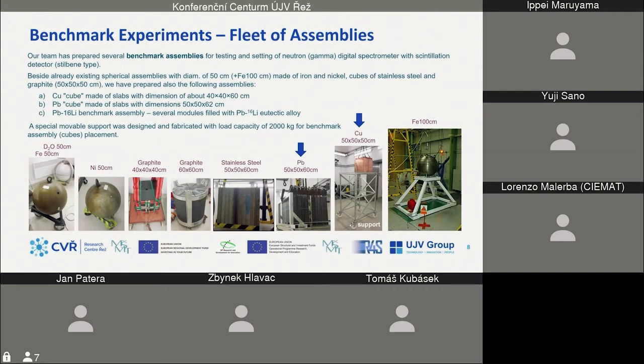And also we have the biggest iron sphere in Europe, with a diameter of 100 centimeters. The assemblies from iron, from lead and copper are intended to be measured as part of the construction material for the fusion facility, as a first wall in the plasma chamber. So again, the experiments that we perform here are focused on the comparison of calculated and experimental data.